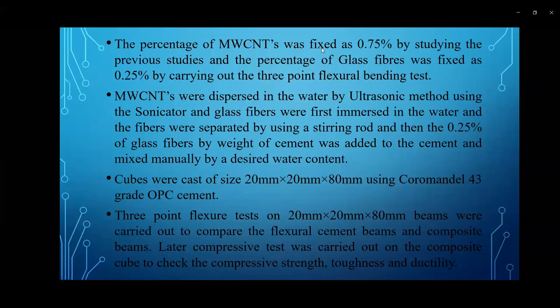MWCNTs were dispersed in the water by the ultrasonic method, and the glass fibers were first immersed in the water and then separated using a stirring rod, and 0.25% of glass fibers by weight of cement was added to the cement and mixed manually with the desired water content. Then the cubes were cast of 20 by 20 by 80 mm. Then a three-point flexural test on these beams was carried out to compare the plain cement beams and composite beams. Later, a compression test was also carried out on the composite cubes to check the compressive strength, toughness and ductility.